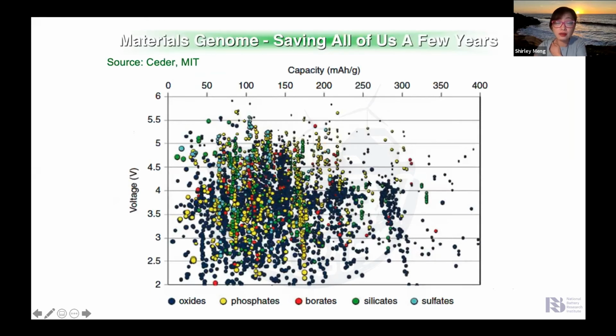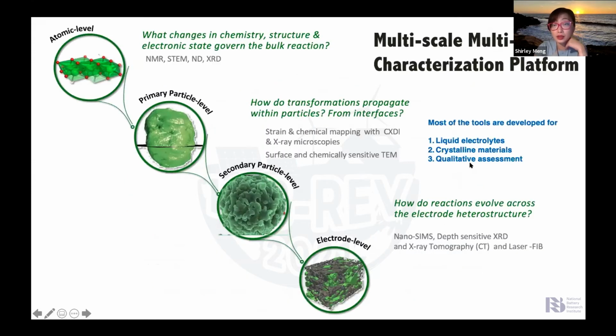The other important thing that happened in our field over the last 30 years is that almost all the known compounds in the database, if they have not been experimentally explored, have been computationally evaluated for whether they are good battery materials. Typically we look for suitable voltage and lithium intercalation capacity. So again, oxides are very attractive, because there are several oxide candidates in the right range, and they can provide very, very high capacity.